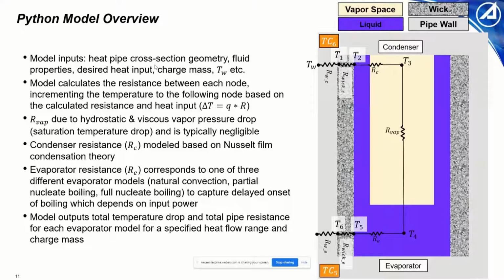The reason for this is that we were noticing through our testing that the onset of nucleate boiling, which depends on a wider range of factors, including your input power and basically the temperature difference between T5 and T4, was delayed. And because of that delayed boiling behavior, we wanted to be able to capture the different modes that the heat pipe could be operating in. So in doing so, we end up with 3 unique solutions for every heat input value.